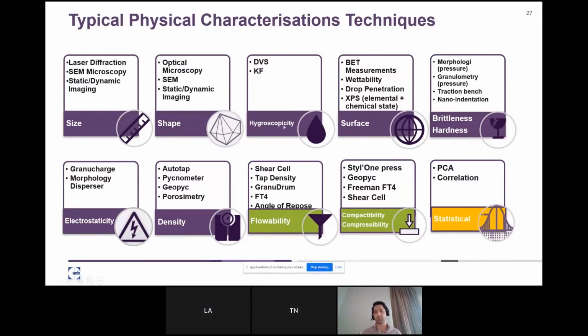Hygroscopicity is how much water uptake we have. The surface measurement is either the surface energy, specific surface area, or the adhesion. Brittleness is the extent of breakage as the particles go through the processes. Then electrostaticity, because we have organics, so they tend to get electrostatically charged, and that could sometimes cause problems during tableting, for example. Then measuring the density. Flowability is, of course, one of the biggest issues, because the powder needs to flow through the process. And of course, compactability and compressibility are also among the major characterizations we do.